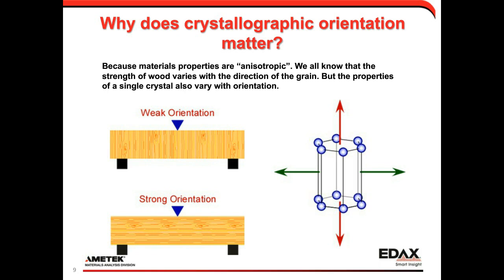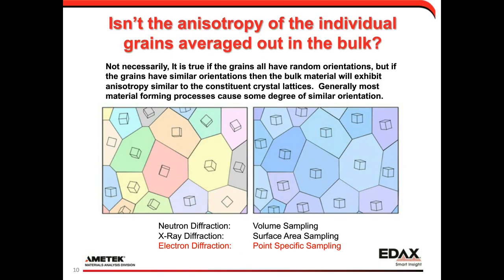That same concept can apply on a crystallographic scale, where some orientations will be stronger, some orientations will be weaker, and different properties will vary in different directions. Now, often when you first start learning about this, it's assumed that when you get enough grains together pointing in enough different directions, the anisotropy is averaged out and it becomes isotropic. This isn't necessarily always true. Most forming and fabrication processes will introduce some amount of anisotropy into your final material. And so being able to measure this is important. You can use neutron diffraction to measure a volume or X-ray to measure an area. But with EBSD and electron diffraction, we can go to very point-specific sampling. And what I'm going to try to do is show some advantages of this approach.